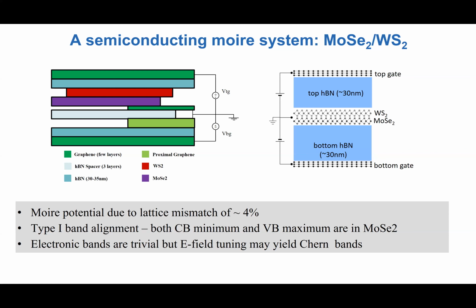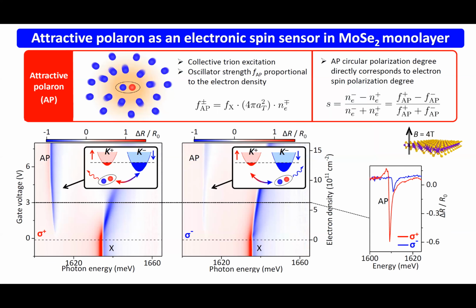Yes. I have a question. Why, if you apply a magnetic field, can it be part of the sample? That table of Landau levels. Yes. You apply a magnetic field in plane. Then you have no Landau level. That's correct. You have the same number. Yeah, but so that's the important point here that when I apply an in-plane magnetic field, at least reasonable magnetic fields, and I even consider 16 Tesla reasonable, nothing really interesting happens. And the reason for that is something I kind of skip, that in these K and K prime valleys, there's very strong spin orbit interaction.